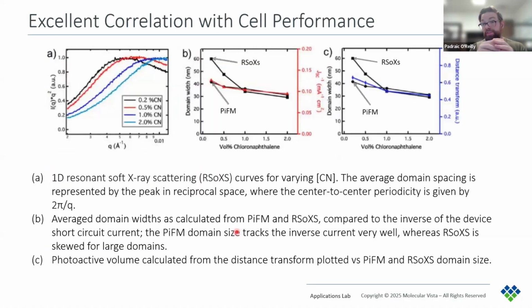So they also used resonant soft X-ray scattering to measure the average domain width and compared these results and those from PiFM with the cell performance. Now these are plots B and C showing these results. B shows the short circuit current and C is the photoactive volume.